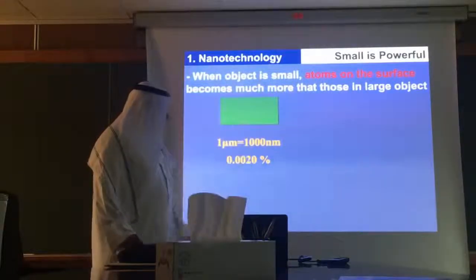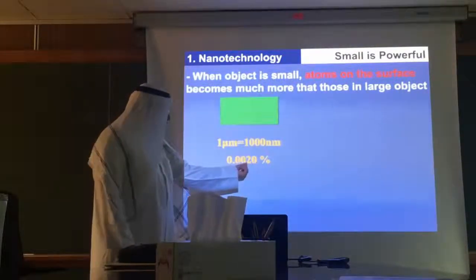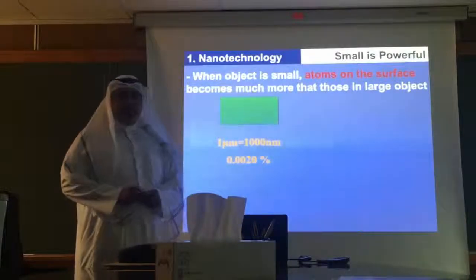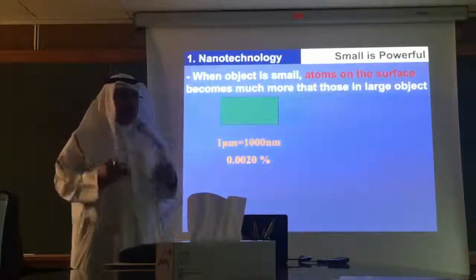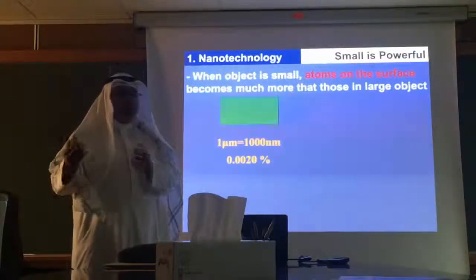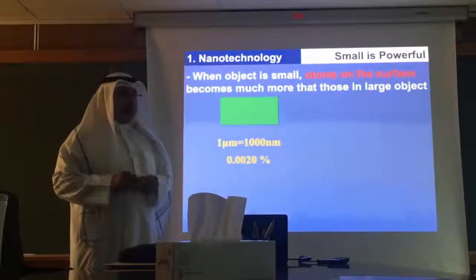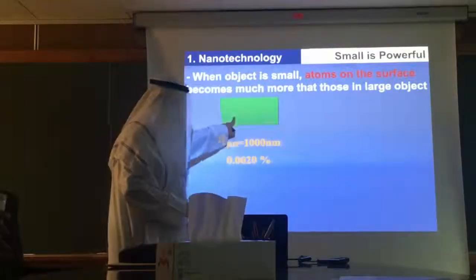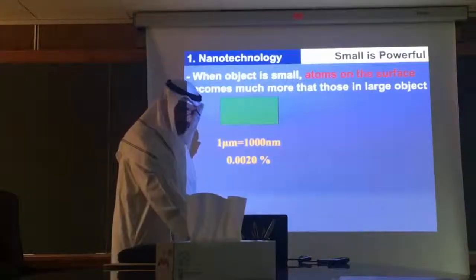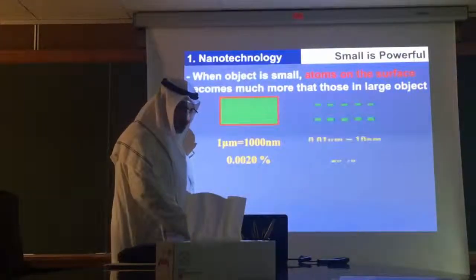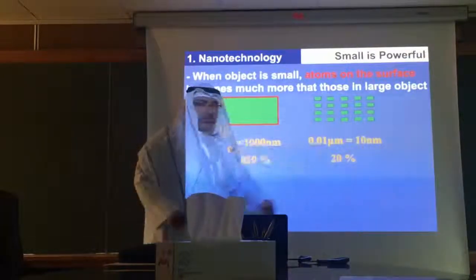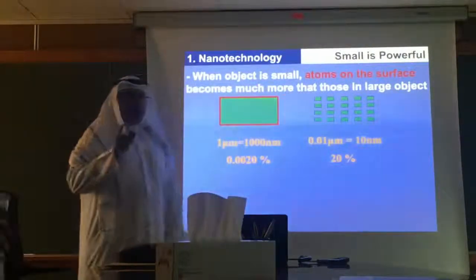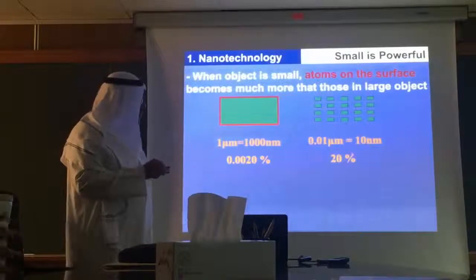Let's say this is 1 micrometer in size, 1000 nanometers. There is only 0.002% of the atoms on the surface. The remaining is in the bulk. So more than 99.8% of the material is hiding in the bulk, and only this small fraction is on the surface.